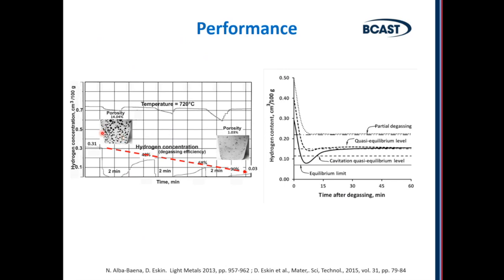You can see here that you can efficiently, in a few minutes, degas from 0.3 cubic centimeters of hydrogen per 100 grams of aluminium to below 0.1. There are also processes of partial degassing, or really deep cavitation degassing, and depending on the level of gas which you achieve in liquid metal, you can have either stable degassing effects, so that you can degas, and this liquid metal can stay there for minutes or probably even hours before casting, and you will have this lower level of hydrogen.